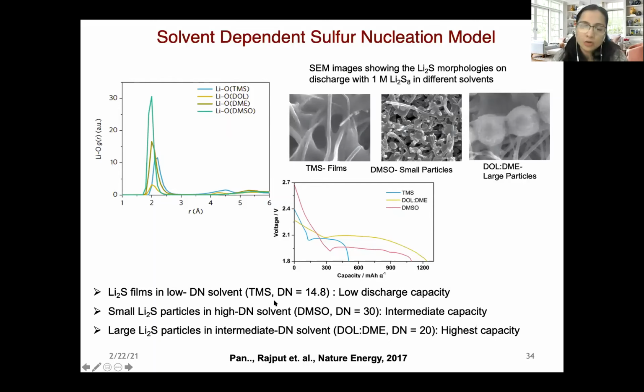we found that if the donor number is too low, like in the case of TMS, then the solubility is very low, which results in precipitation of lithium polysulfide species at the electrode, which forms this insulating film-like structure, because of which the discharge capacity is very, very low.